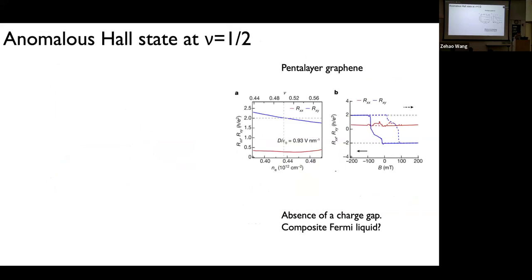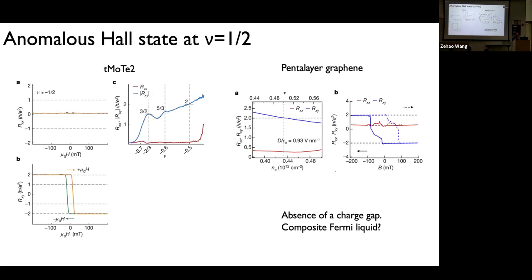One last thing I want to mention is that now, in addition to discovering 0 field FCI, they also saw some anomalous behavior at what's called half filling. This attracted a lot of attention in the context of fractional quantum Hall effect, because there's this notion of composite Fermi liquid and more exotic stuff happening. Again, the phenomenology between these 2 distinct material platforms looks very, very similar. There's hysteresis, there's no charge gap, and at this level it seemed to be consistent with a composite Fermi liquid, and people are working on that.